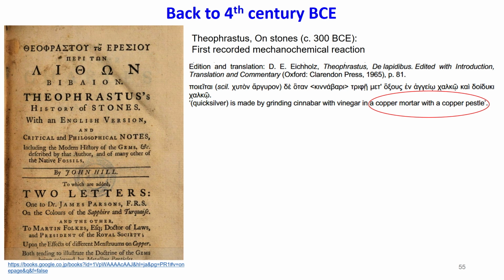And this actually takes us back to the 4th century BC to show how chemistry is connected through all this time. Because you see in this procedure of Theophrastus that he used a copper mortar and copper pestle. And as historians mention, in this ancient procedure, it's very hard to know which part of that is important, which is not. But luckily, more detailed studies were performed recently, in particular in this work by Italian authors. So collaboration between historians, philologists, and chemists, where they try to study this process. And cinnabar that was used as a precursor is actually mercury sulfide, and the copper that was present in the mortar with a pestle is actually the reagent.